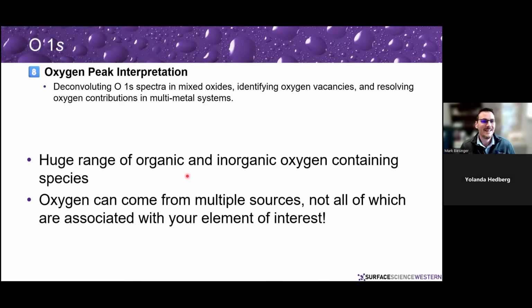If we look at the oxygen peak, that was another big question that we wanted to look at. Oxygen can have a lot of sources, and people get focused on it. They say, "Oh, I'm looking at cobalt oxides, so I want to look at the oxygen peak." But then they don't realize that they have other sources of oxygen available in their sample that are contributing to the oxygen peak. And so with oxygen, you can get a huge range of organic and inorganic oxygen containing species. It can come from multiple sources, not all of which are associated with your elements of interest.